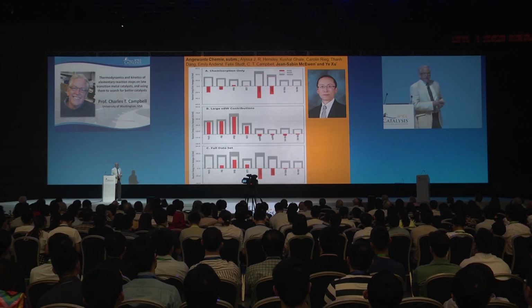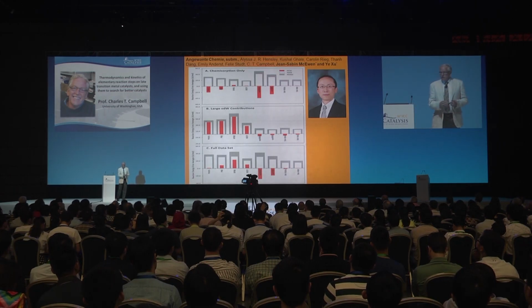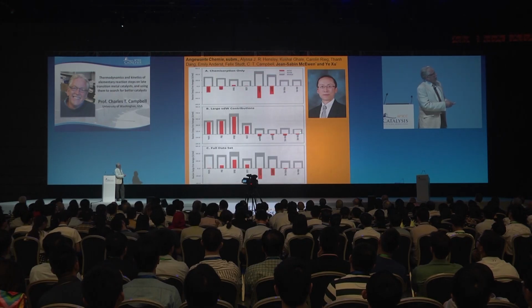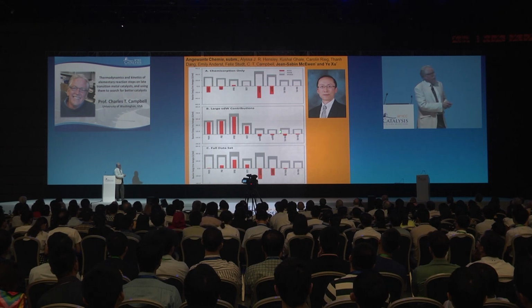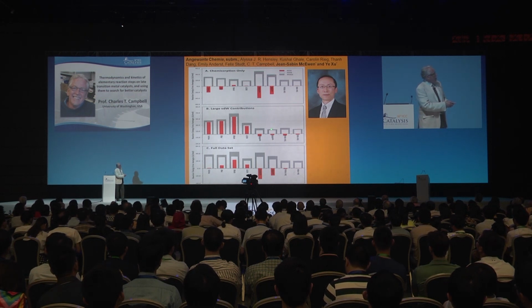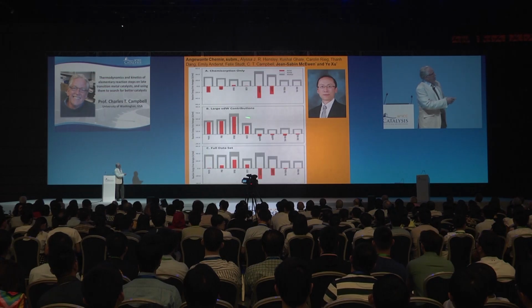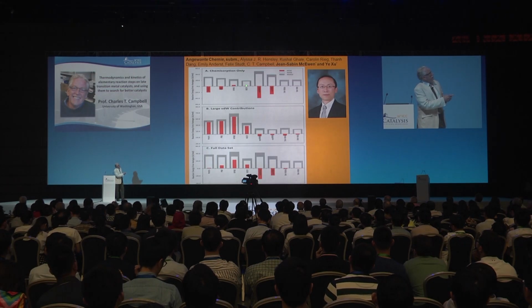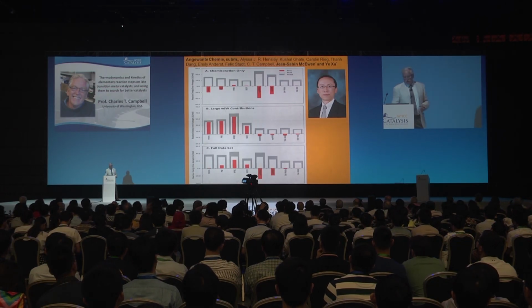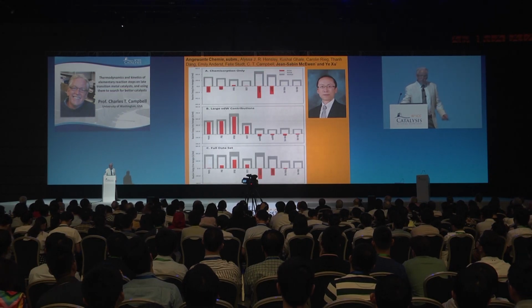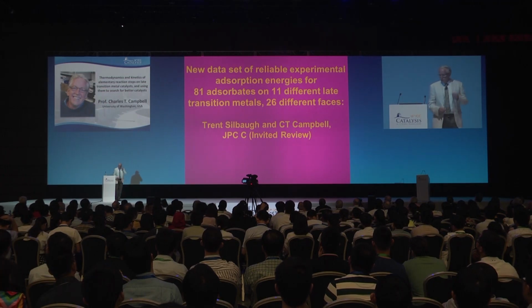But we put together a method to combine RPBE with these optB techniques to get a new DFT-based approach for estimating adsorbate energies that's more accurate by far than the other techniques that are much more commonly used, and almost as accurate as BEEF for the smaller adsorbates, so that the overall errors are the smallest for this new methodology. This paper was just submitted to Angewandte Chemie.